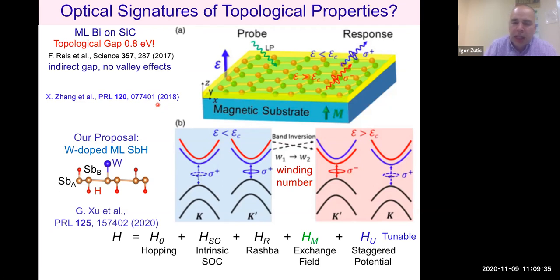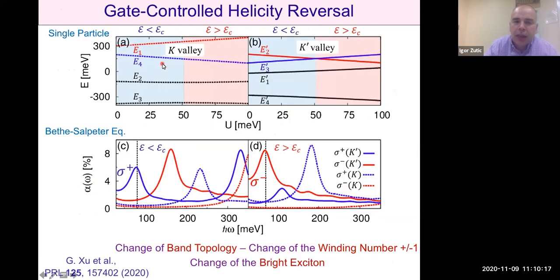the emitted light. One possibility would be to have a magnetic substrate, or maybe one can add magnetic dopants, and we focused on antimony, hydrogenated antimony doped with tungsten, because we have inequivalent Sb sites. Then effectively, in addition to standard terms in the Hamiltonian, hopping, intrinsic spin orbit coupling, or Rashba spin orbit coupling, or even exchange field, there would also be a staggered potential, which could be further tuned by electric field. So if we now consider what this means at the single particle level, by applying an electric field, we can create a band crossing not at K, but at the K prime valley.